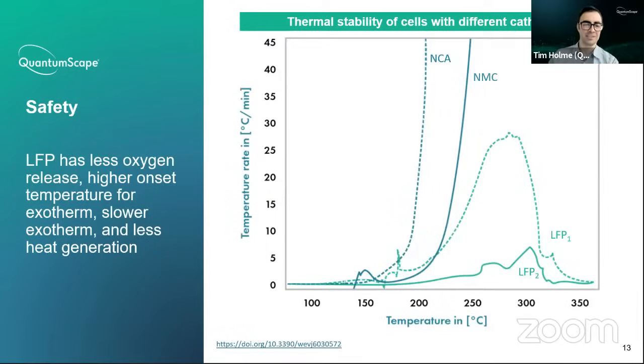LFP, as Sam mentioned, has improved safety properties as well. There's less oxygen release from the LFP crystal structure at high voltage. In an overtemperature event, there's a higher onset temperature for exothermic events. It's a slower exotherm and also less heat generation. So if there is an overtemperature event or a safety event, as there will be in cars that crash, it's fundamentally a safer chemistry. This slide is one way to illustrate this.